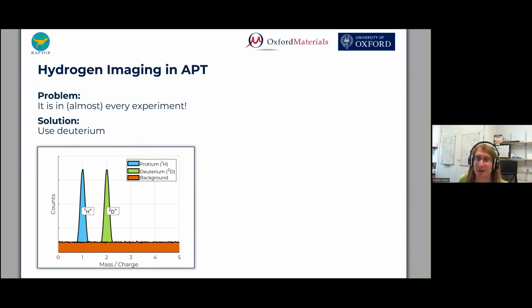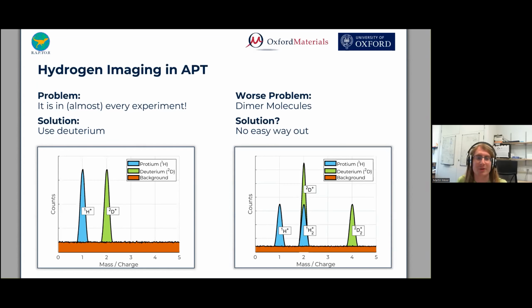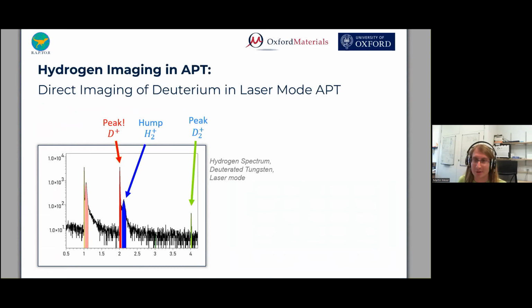But this is not working if your sample just decides to evaporate dimer molecules, the hydrogen 2 plus, because then in your spectrum, you will get this overlap of contaminant H2 plus and sample deuterium, and there's no way you can work out what is coming out of the sample and what's contaminant. This is no longer strictly true. We have shown that if you get the parameters right, you can produce an energy deficit in contaminant hydrogen, which means you can now tell apart the hydrogen, the deuterium from the sample and the contaminant hydrogen.